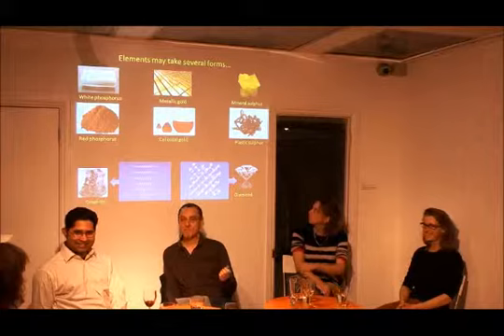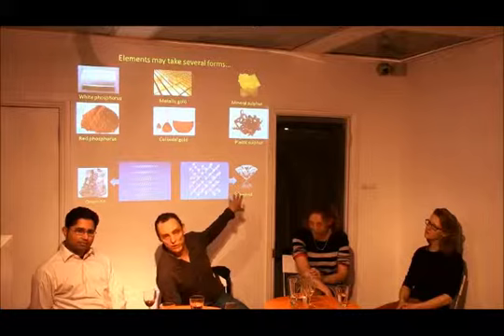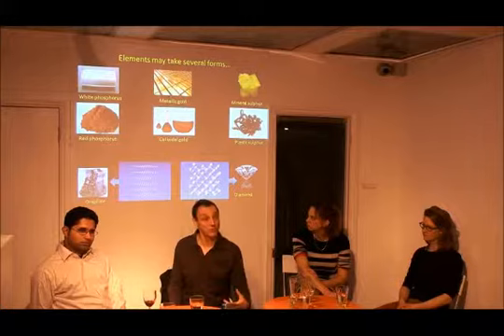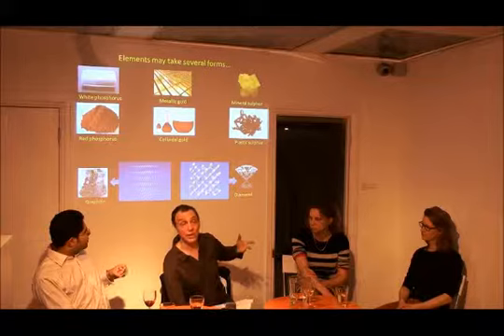No. Carbon black is amorphous, so it doesn't have this sort of regularity, this crystalline structure. It's much more disorderly in the way the atoms are arranged. This kind of bonding pattern in graphite is what gives it this blackish appearance. It's what allows it to absorb most of the light that falls on it in the visible part of the spectrum. It also accounts for why graphite slightly conducts electricity, and that's important technologically. And it's what gives graphite this sort of silvery metallic sheen.